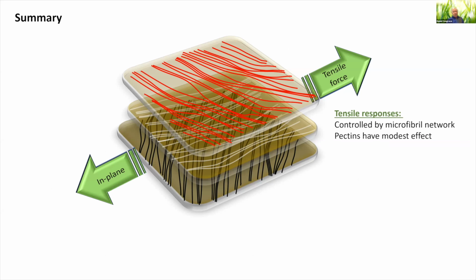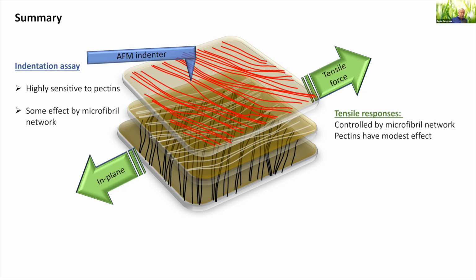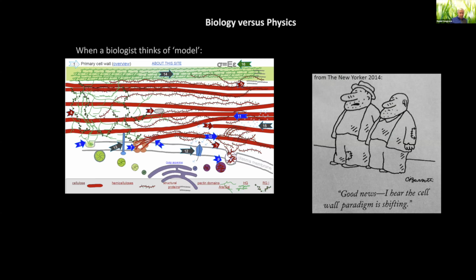And so from these kinds of and related studies, we can learn that the microfibrils in the cell wall are the dominant controlling factors for the tensile responses, so stretching in plane of the cell wall. Pectins have a very modest effect. From the indentation, however, pectins are important. They're influencing how the wall responds to indentation behaviors. And there is a smaller effect of microfibrils.